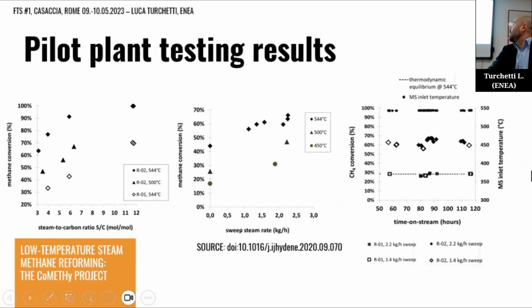So what you see here, with this feed that we had for the reactor, the conversion was around 30%. Around 30% of the methane we fed was converted into hydrogen and carbon dioxide, which is basically what the dashed line is: the thermodynamic limit if you don't put a membrane at those temperatures. So it's very low. And here you see the conversion you get with a membrane reactor, which is basically almost double that of a conventional reformer.